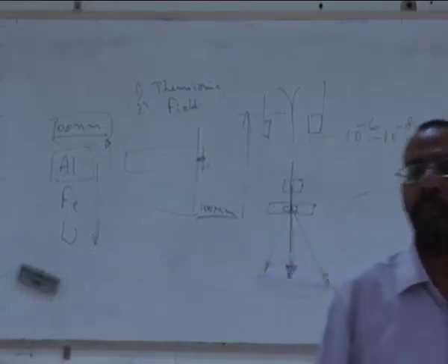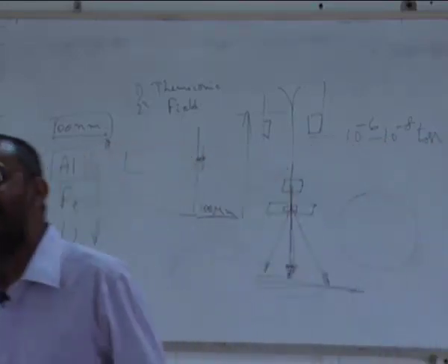This is exactly what I faced when I was working with Tata Steel people. There was a lady who used to come to our IIT Madras to do a lot of microscopy, electron microscopy, TEM. She used to prepare her samples there and bring them here and put them into our TEM and we used to see them. Every time I put a sample in, we used to see a lot of dislocations. I used to say, what is happening to your sample? Why is it so heavily deformed? She said, no sir, my samples are all annealed samples. Your microscope is bad. So I used to say, microscope is like garbage in, garbage out. What you put in is only what you see. It does not create anything. TEM cannot create dislocations inside your sample.